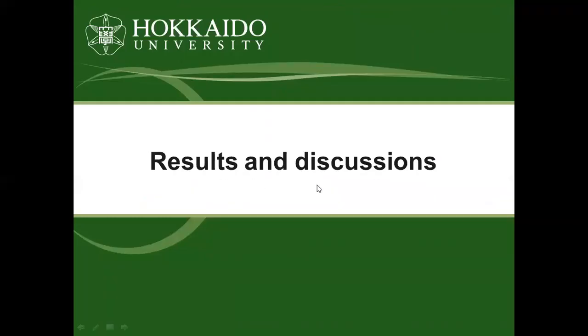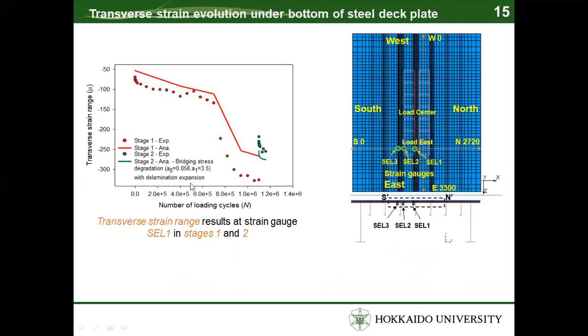Results and discussions. These figures show the transverse strain range result at the strain gauge SEL1 in the steel deck plate. In stage 1, due to the occurrence and expansion of the delamination area at UHPFRC-steel interface, a significant increase in the strain range level could be obtained in this stage.